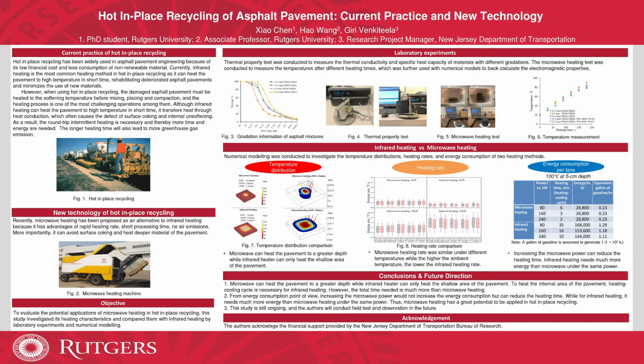But when we use HIR, the pavement must be heated to the softening temperature before mixing, placing, and compaction. Although the infrared heating can heat the pavement quickly, it transfers the heat through heat conduction, so it often causes the defect of surface cooking and internal unsoftening. So recently, microwave heating has been proposed as an alternative to infrared heating because the microwave heating has advantages of rapid heating rate, short processing time, and no air emissions. And more importantly, the microwave heating can avoid overheating the pavement surface and can heat deeper material of the pavement.